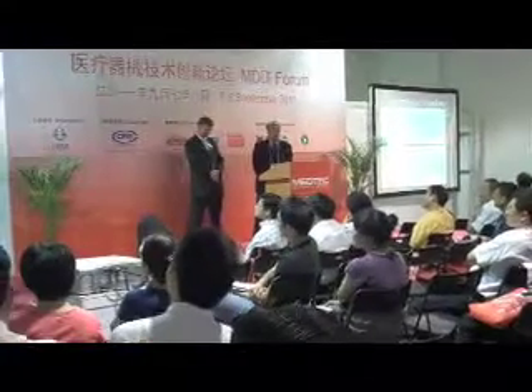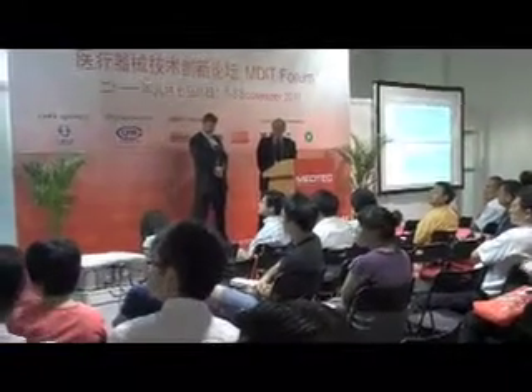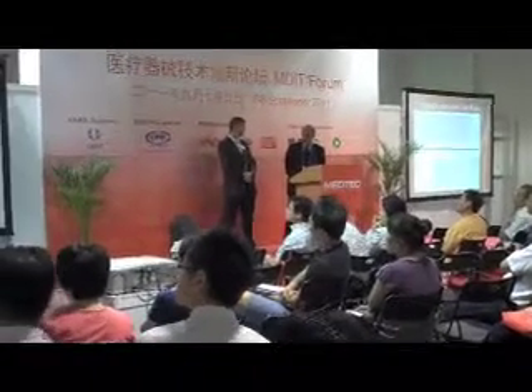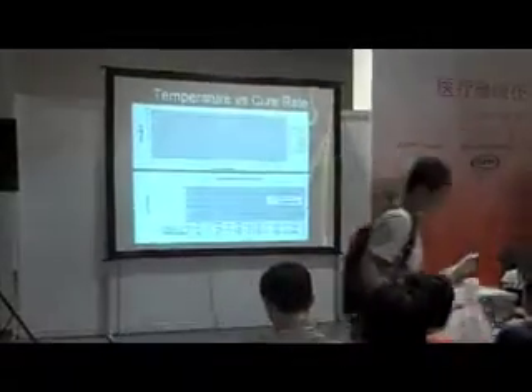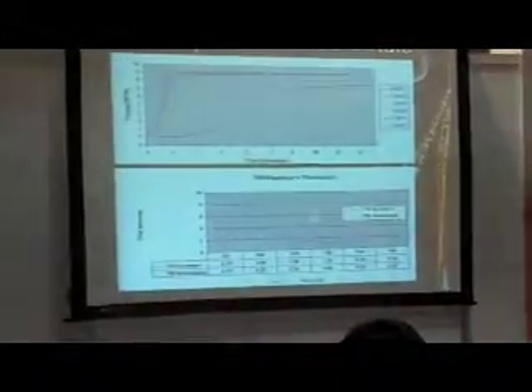So there you see it. The 5 different temperatures produce different cure rates. On the bottom, we've taken one representative variable, if you will, that being T90, the time at which these materials were 90% cured. And we plotted them both theoretically and empirically, and you can see that the silicones do in fact correlate well with the Arrhenius equation.